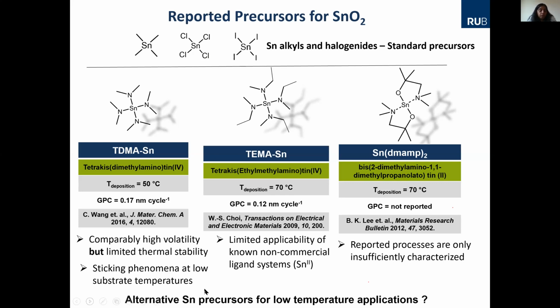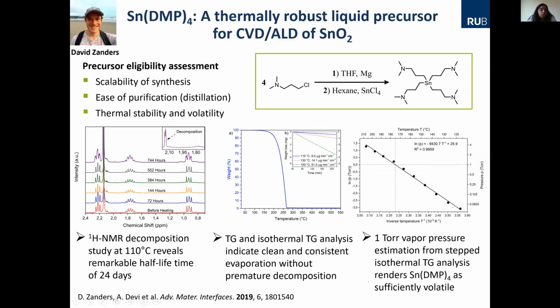So what was our aim? To look for alternative tin precursors for low temperature. My doctoral student, David, looked into this aspect where he used the same ligand, the DMP ligand, that I mentioned for you in the case of aluminium. He made a tin precursor and looked into the purity in terms of NMR, mass spec, elemental analysis, and then the thermal properties. Here you see a beautiful TG pattern, a thermal analysis pattern where weight loss is a function of time, and the precursor sublimes with absolutely no residual mass, so it's cleanly volatilizing. Vapor pressure is also determined, that means what is the optimal pressure in the reactor at a certain temperature. All these characterization techniques render this precursor very appealing both for CVD and ALD.